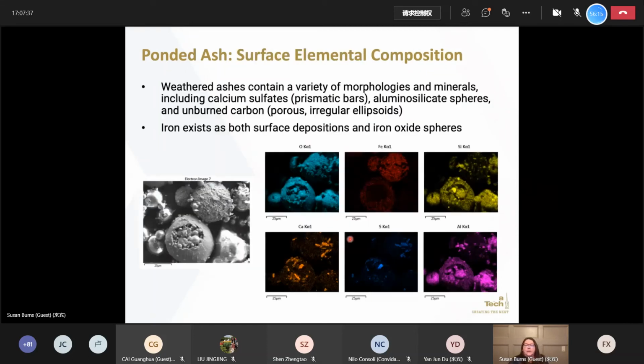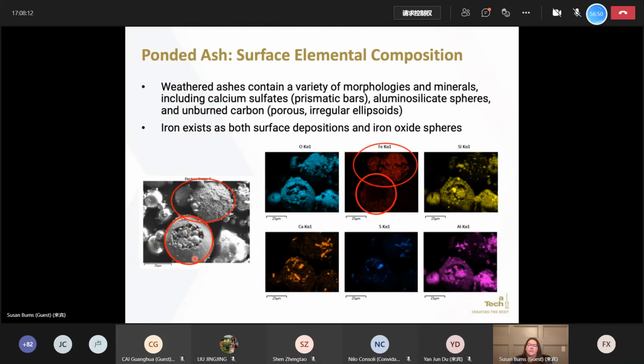In addition to that, what we're going to see is that over time, as these ashes age, they're going to change not only their morphology, but also their mineral phases. And so here on the left-hand side, we've got an SEM image of some typical ash that we've taken from the pond. And then on the right-hand side, we have the elemental map. And what you'll see is that if we look at where the calcium and the sulfur coincide on the surface of these ashes, we'll see places where calcium sulfate has precipitated and formed a new mineral phase on the ash itself. In addition to that, what you'll see is we can find the occurrence of iron on the surfaces themselves.